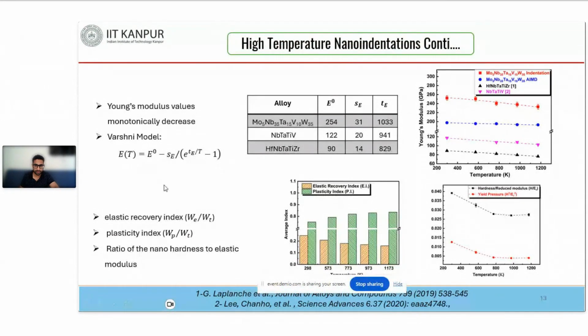After the modulus measurement, we got a load indentation curve, and from the load indentation curve we can measure the elastic recovery index. The elastic recovery index is the ratio of energy released during the unloading part of the curve to the total energy absorbed during the curve. It decreases monotonically as a function of temperature, which is similar to the Young's modulus variation. But for the plasticity index, there is an increase in plasticity up to 773, and then an almost constant value of plasticity beyond 773. This behavior is similar to the hardness variation.